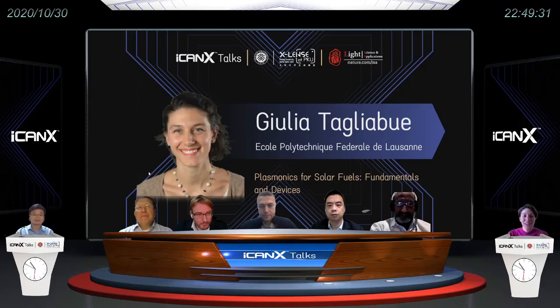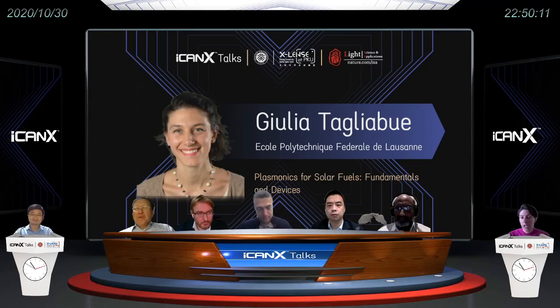Well, that could be another way. I'm not sure there have been reports in that respect. That is more of a high temperature process. So there could be some advantages related to the local photothermal heating that can be obtained with plasmonic nanoparticles, which we know can produce very strongly localized temperature at the nanoscale. And because they're also the catalyst, now you are able to selectively heat up the catalyst without having to heat up a huge, bulky heating system. So this could also be, going forward, an application of these plasmonic systems that overcome some of the challenges of macro scale devices. Okay, good.